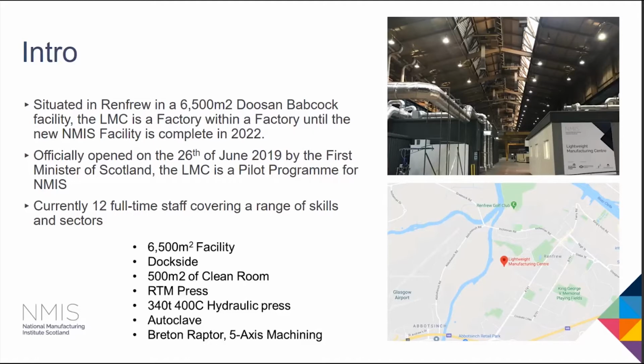The launch capabilities: we have 500 square metres of Class 8 clean room. We have one RTM press. We have one 340-ton press with heated platens to 400 degrees C, which enables us to develop materials up to the high-end semi-crystalline thermoplastics. We also have an autoclave and a Breton 5-axis machining cell, which has a high specification, so we can machine down to 7 microns locally and 20 microns within the area, which is about 20 square metres.